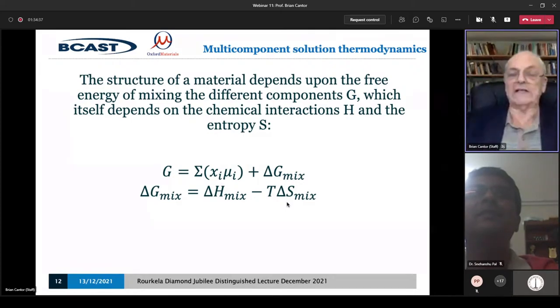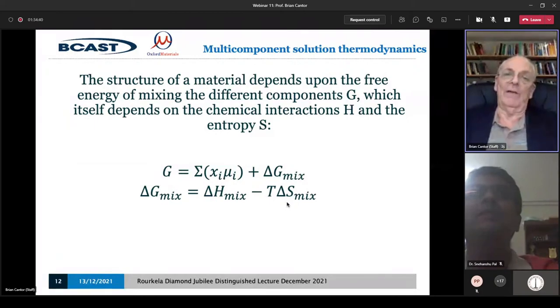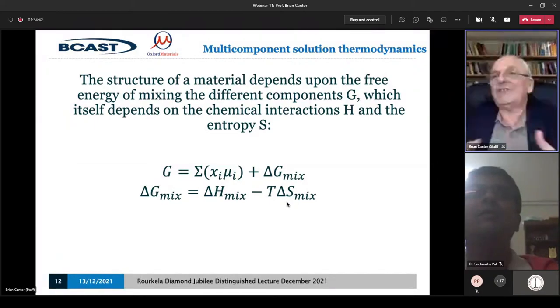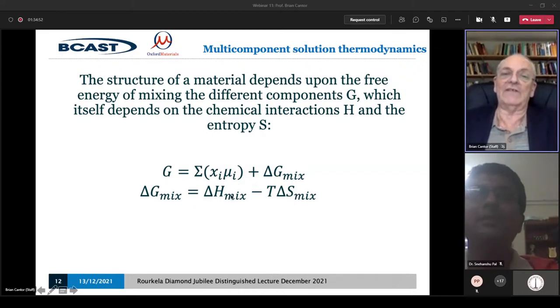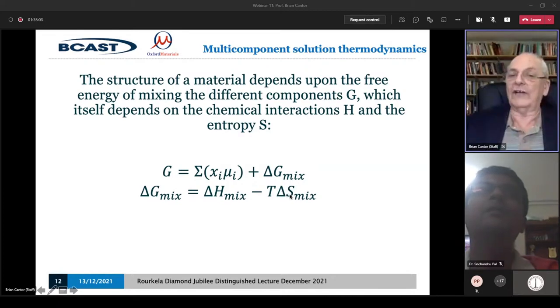Now, you're right. Of course, at first people were surprised, because they didn't expect to find these multi-component single-phase materials. They were surprised they were so easy to make. The reason they're so easy to make is that the entropy effect, as I've already said, is big enough to dominate. But it dominates at high temperatures, for sure. But as you go to low temperatures, it gradually must still drop out. The question is, how low a temperature will it go?